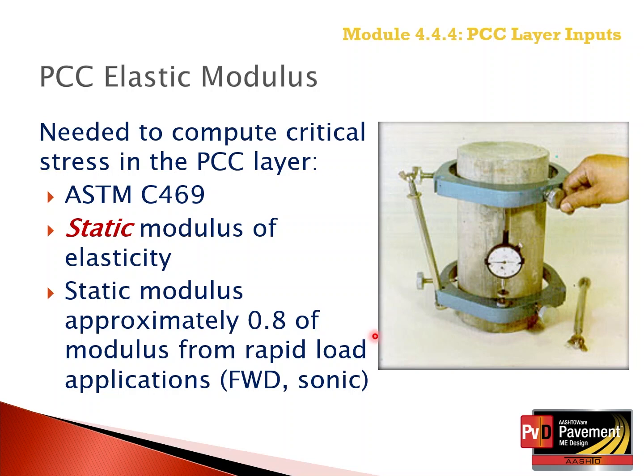The static modulus is about 80% of the elastic modulus determined from rapid loading conditions, or approximately 0.8 of the modulus measured from rapid load applications.